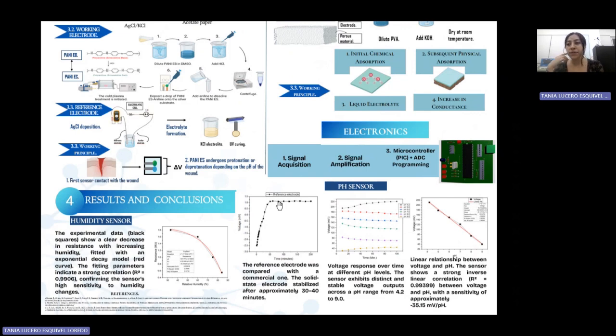Now, for the testing procedure, the humidity sensor was tested by exposing it to controlled humidity chambers and measuring its resistance. And the pH sensor was tested with standard buffer solutions ranging from pH 4.2 to 9.0. And the reference electrode was compared to a commercial electrode from a laboratory pH meter to determine the stabilization time. All data were analyzed to establish correlation, sensitivity, and linearity. And for the last part, the results and the conclusions.